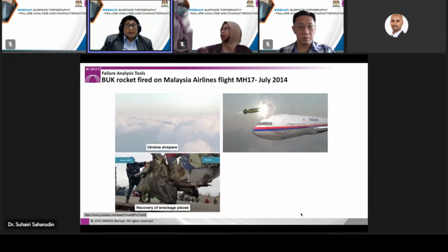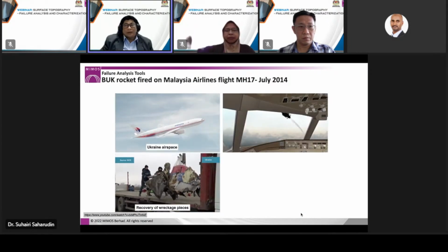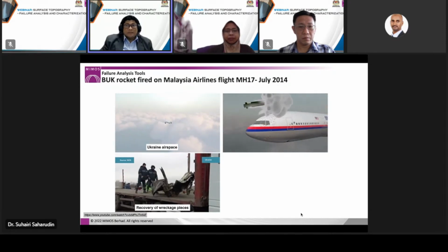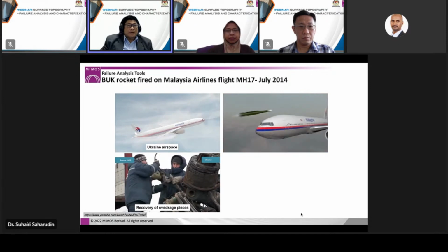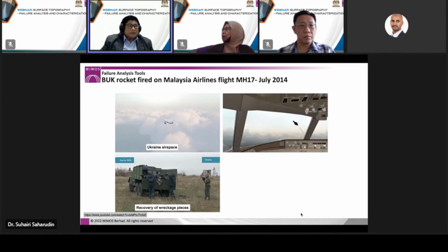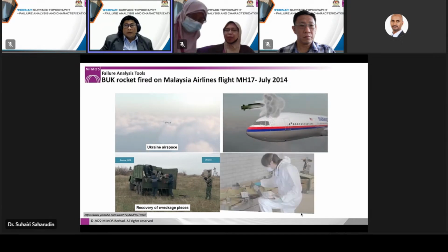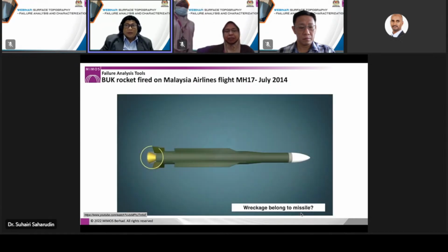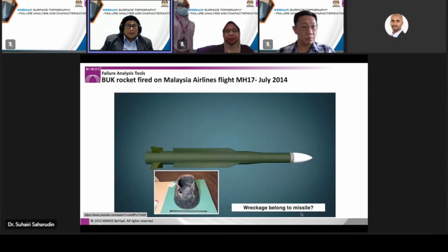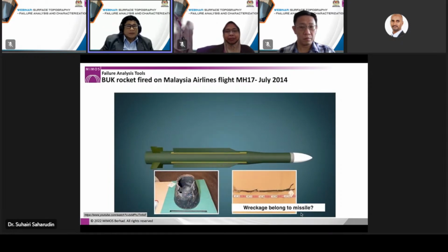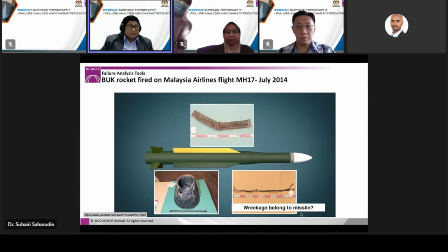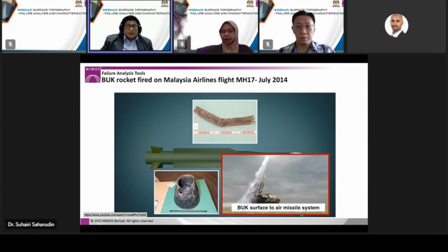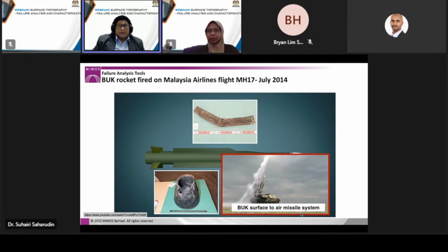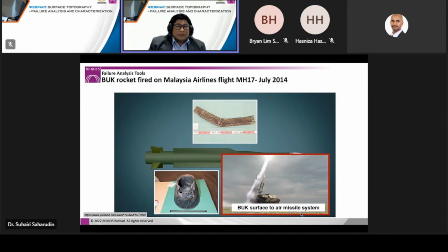Similar forensic approaches were adopted in determining the crash of flight MH17 by comparing the paints from the found wreckage with the paint element used in a type of missile. In the analysis, it was found that the identified paint matches the paint of recovered missile parts, which was found inside the aircraft cockpit. This finding led to a hypothesis by the Dutch Safety Board that the downing of flight MH17 was caused by a missile launched from a BUK surface-to-air missile system.